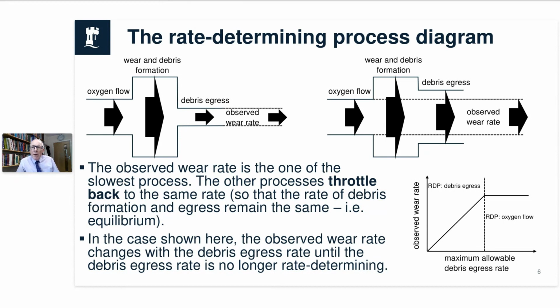What we then see is that as we push the debris egress up, as it were, that part of the pipe gets bigger. Look at the figure on the bottom right there. As we push up the debris egress, the overall wear rate will increase as we move from the left-hand position to the right-hand position. The wear rate will increase until it's stifled, in this case, by oxygen flow. The debris egress has got big, and suddenly at a certain point, it stops being the rate determining process.